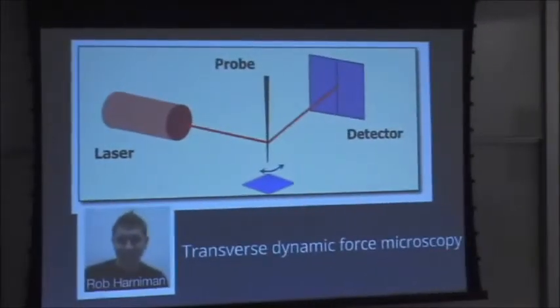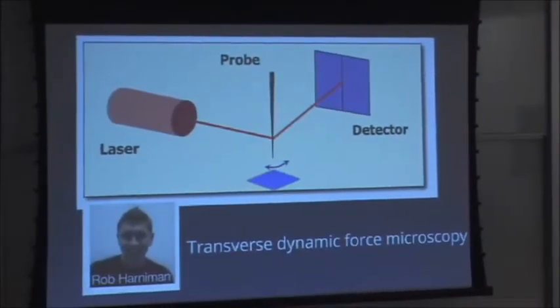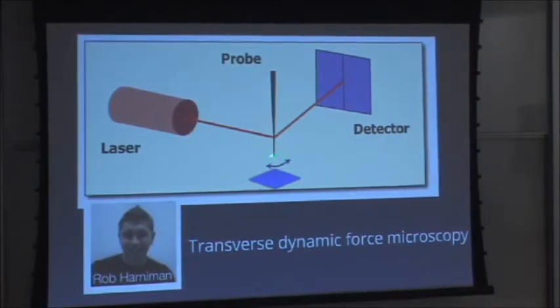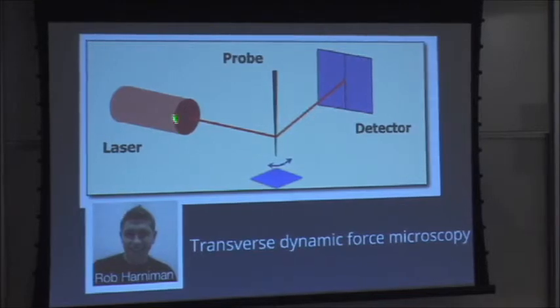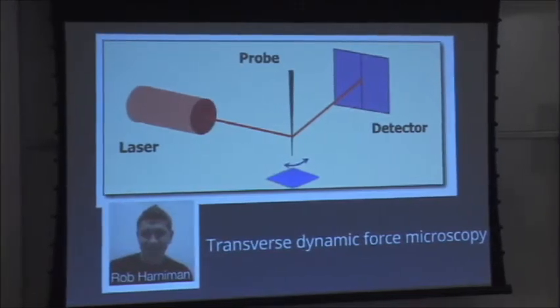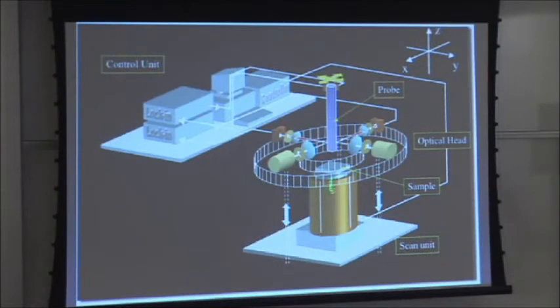So this is an AFM in which we have the tip mounted vertically. So it's very like our near-field optics, our vertical optical fiber. And we do dither it. We move it by about a nanometer at the end, and we measure its behavior with a beam deflection system again. So that's the original version. That's how it looks in reality. Here's the sample. Here's the scan tube. Here's the probe. And then we have two optical detection systems, because now it's circularly symmetric, so the probe might start to do Lissajous figures, and we need to know what it's doing.